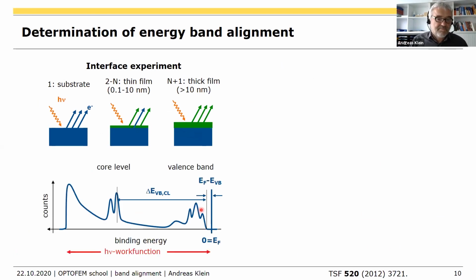Now, this is our potential semiconductor spectrum. And you see from the bare substrate, we get the Fermi level with respect to the valence band maximum. So we get the Fermi level inside the band gap of the material. The other thing we get from this spectrum is the valence band maximum as a distance to the core level. And that's a material constant, which is fixed for a certain material.